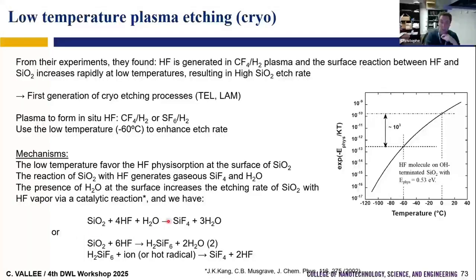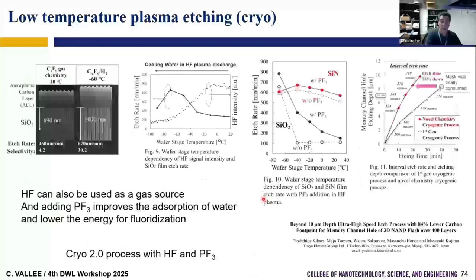So you do not use temperature, you use ion energy. And with ion energy, you promote this reaction, you enhance it, and now you do a lot of etching of silicon oxide, forming SiF4. This reaction was also proposed to explain the fast etching with the CF4/H2 plasma. So this is the idea.